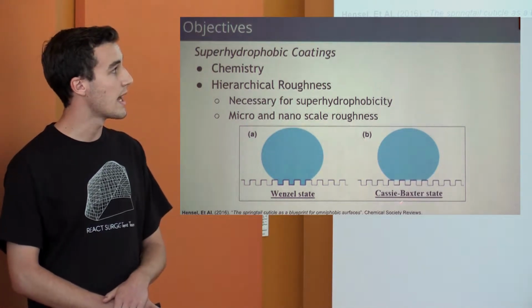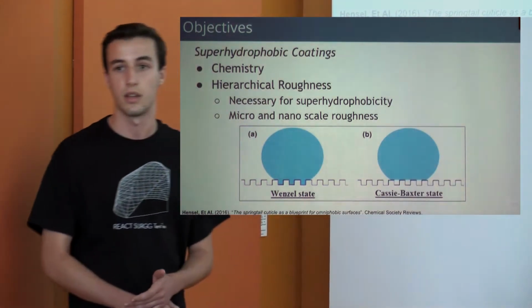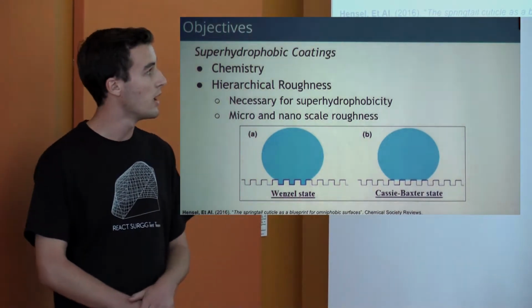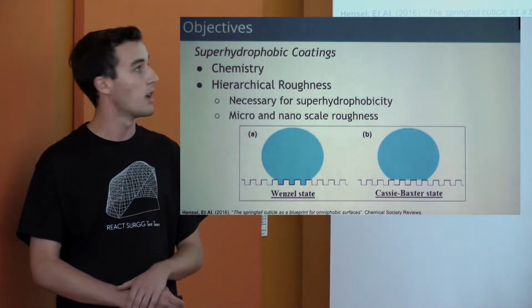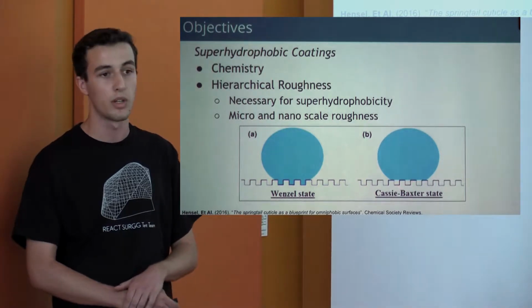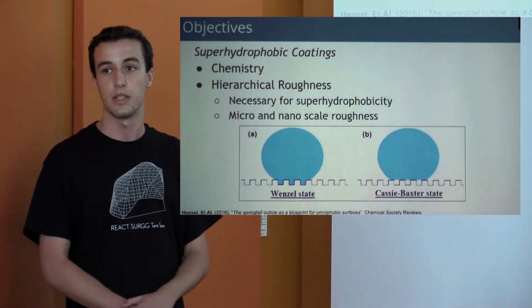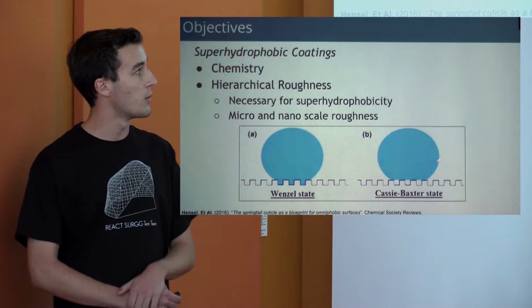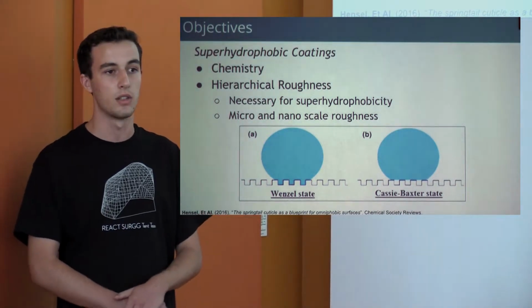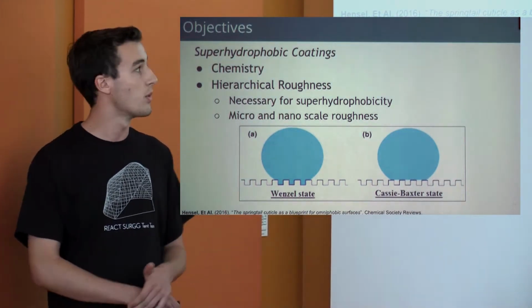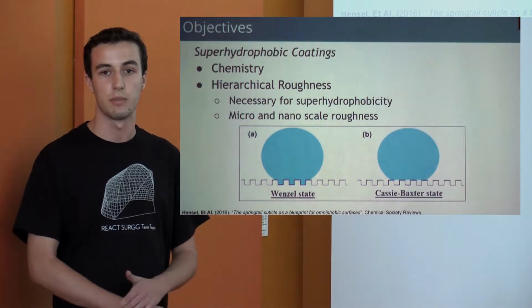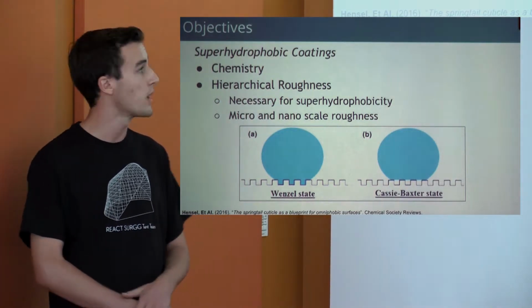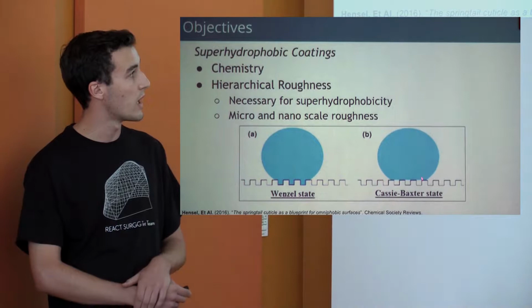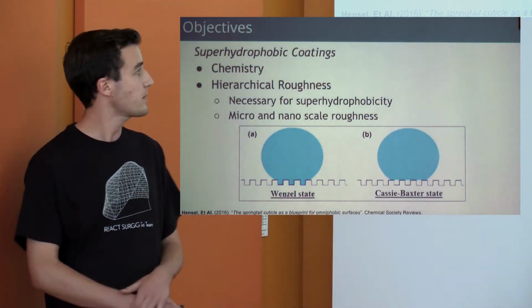Another scenario is the Cassie-Baxter state, which is usually considered more hydrophobic. In the Cassie-Baxter state, air pockets are trapped underneath the water due to the arrangement of the surface structures. Water is defined as having a contact angle of 180 degrees with air, so the more air you can have trapped under the water droplet, the more hydrophobic the surface will be. So we started looking for how to achieve something in that state.